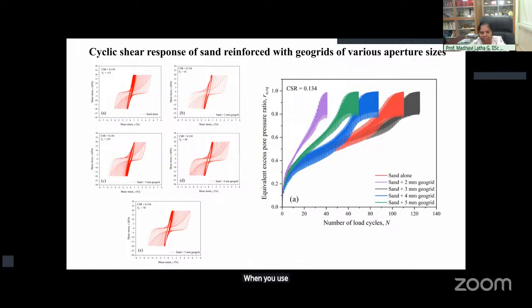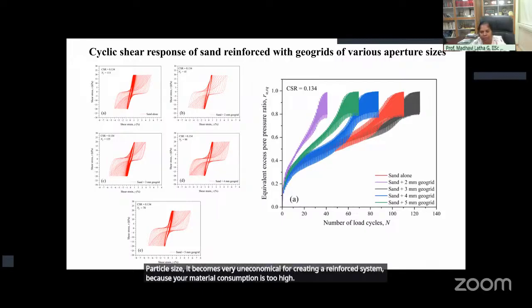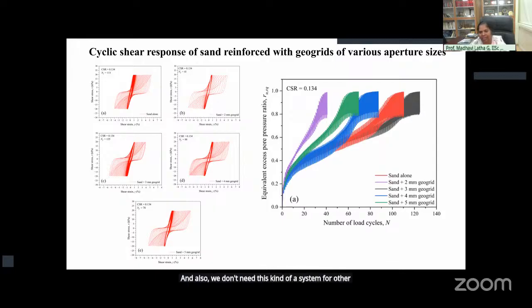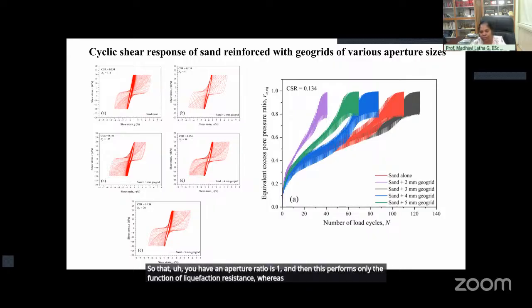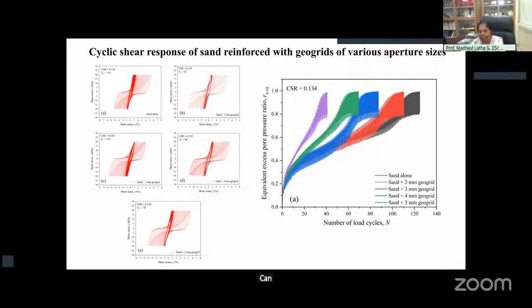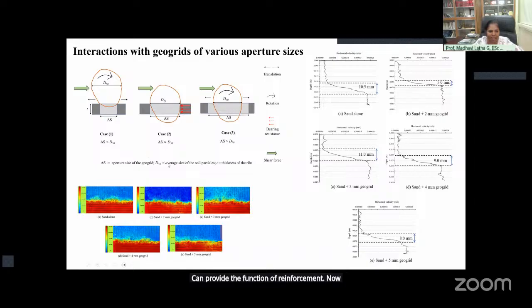When you use a system with aperture ratio matching the particle size, it becomes very uneconomical for creating a reinforced system because your material consumption is too high. And also we don't need this kind of system for other functions. So just to enhance the liquefaction resistance of the sand, we can have one layer of a very low strength geogrid below the actual geogrid which is used for reinforcement, so that the aperture ratio is 1, and this performs only the function of liquefaction resistance, whereas the other geogrid with larger apertures can provide the function of reinforcement.